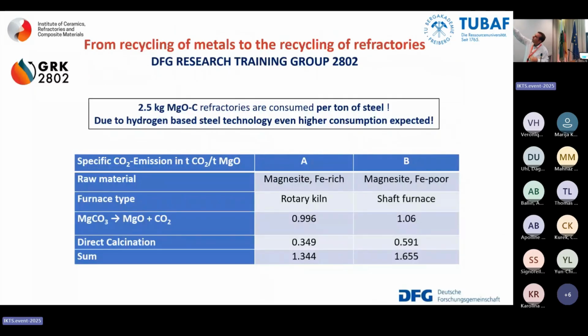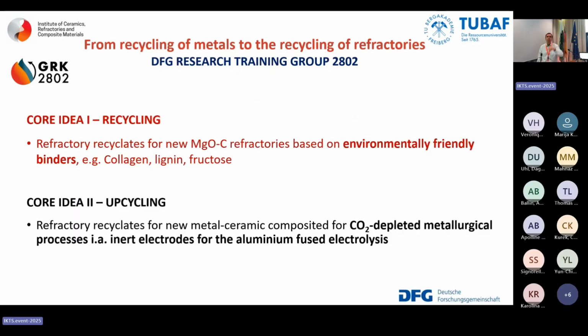Okay, let's go from the recycling of metals to recycling of refractories. It was already mentioned yesterday, according to MgO-C bricks, for instance. And we have 20 guys here with us that belong to a school of the DFG, GRK 2802. This is a number. But the number means that half of them are dealing with recycling. That means they pick up MgO-C refractories and they combine them with environmentally friendly binders. So no pitch, no resin. Let's use tannin, fructose, collagen. Do I get residual carbon at the same height? Do I get the strengths after coking? You can discuss with them today and tomorrow and during the ECerS.